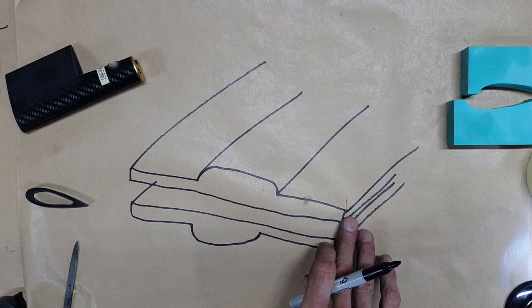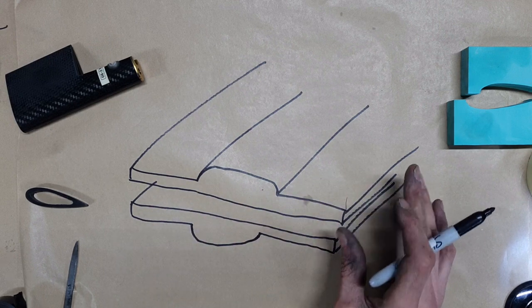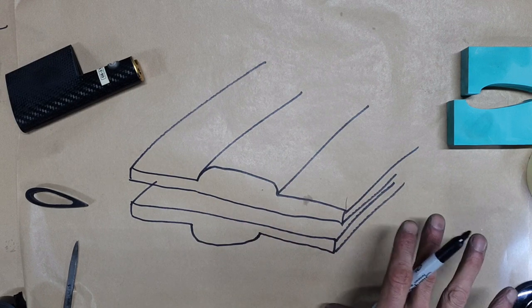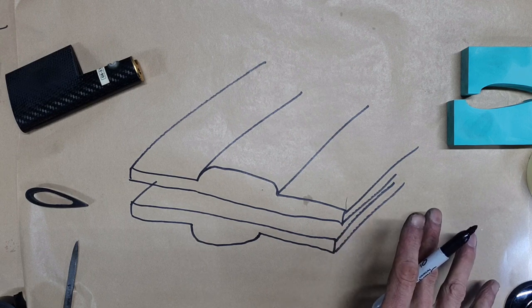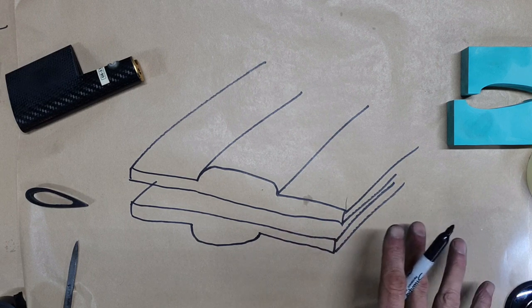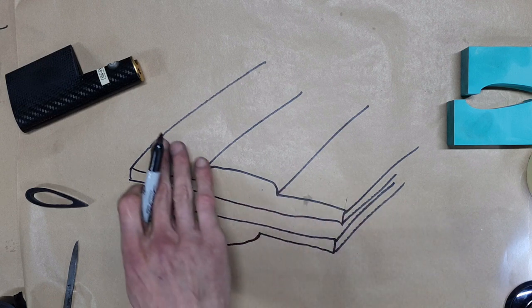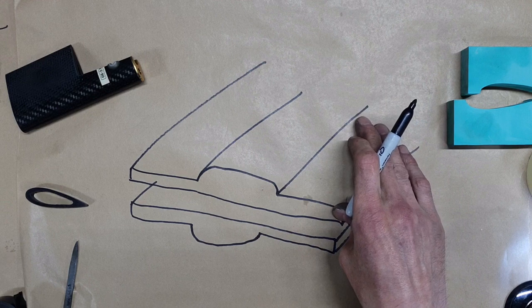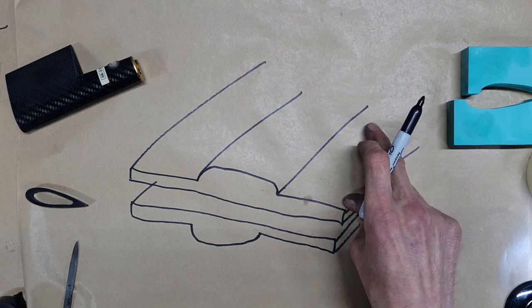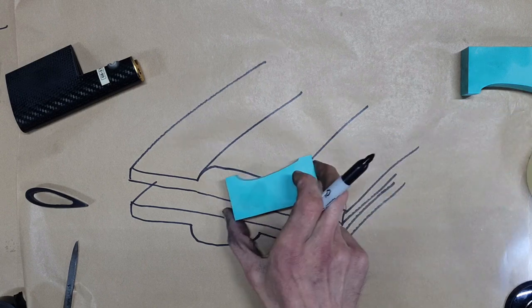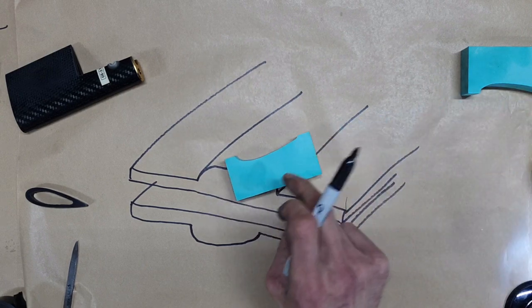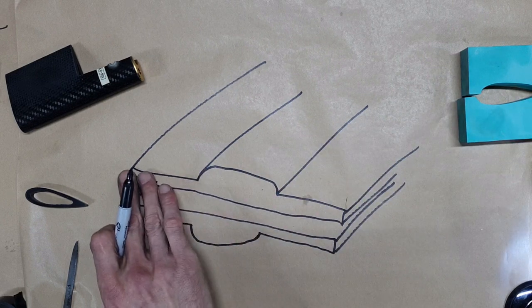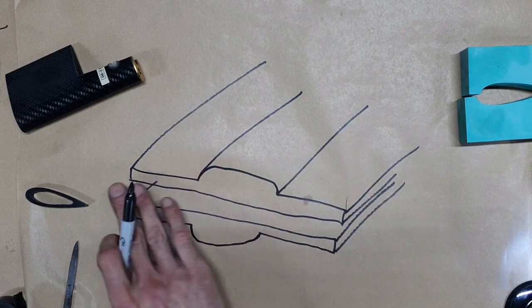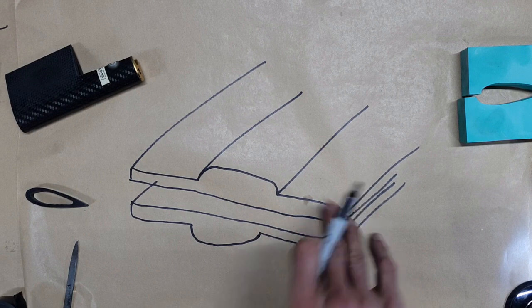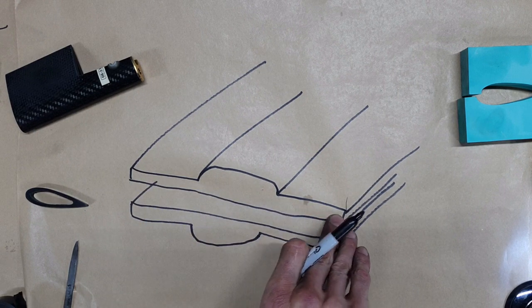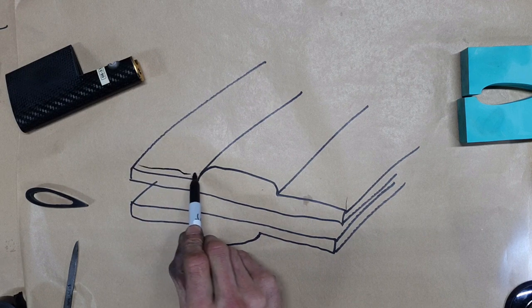So they would then take this tooling plate and lay up what's called, again, pre-preg carbon fiber. Now you'd see a lot of people online in the hobby market or in lesser critical components. They would either pour a tool on here with a polyurethane tooling resin, or machine it directly from this, which is tooling board. But in terms of highly stressed parts, you generally want this in aluminium because it has to go into the autoclave. So they would machine this from aluminium and they would lay up a tooling carbon fiber